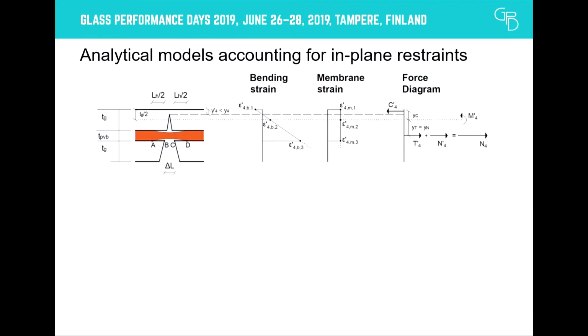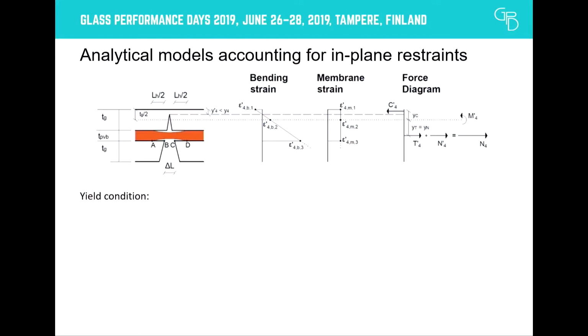In the plastic stage, the combined bending and membrane stresses cannot exceed the yield stress due to the adopted elastic perfectly plastic material law. In this case, we need to define a yield condition in order to ensure that the material law is not violated. This will allow us to determine the relative contribution of bending and membrane forces.